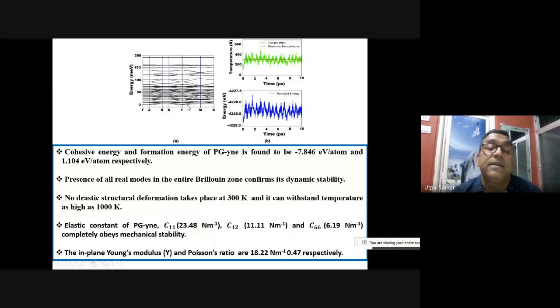We have characterized this material through molecular dynamics simulations at 300 degrees temperature and phonon band structures, to see whether this material is stable or not. Some other characterizations we have done, like mechanical stability, and we have calculated the Young's modulus, Poisson's ratios, etc., and the coefficients C11, C12, C66.